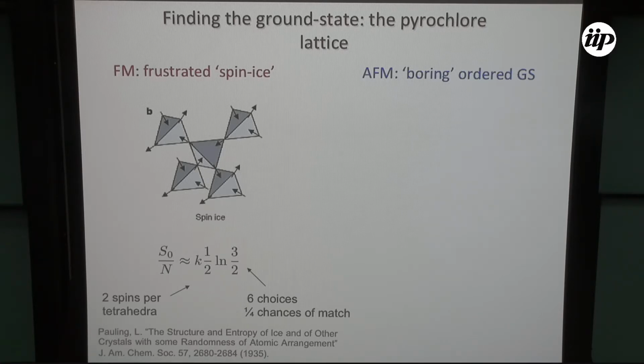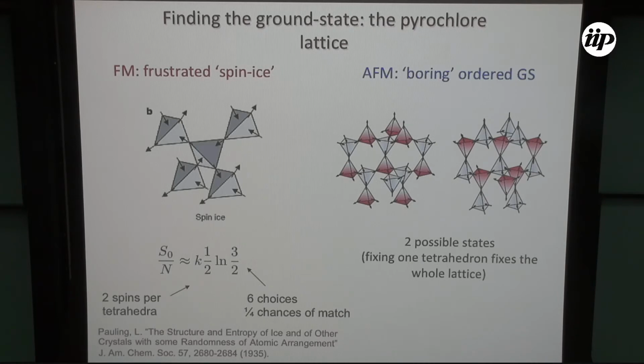Essentially, in this extremely simple model, we're not taking into account more than nearest neighbors. You see that the entropy you get is the same as the entropy you get for hydrogen in water. So essentially, the states of pointing in, pointing out are equivalent to being covalently bonded or hydrogen bonded, like in water.